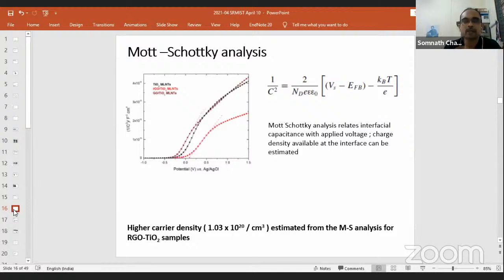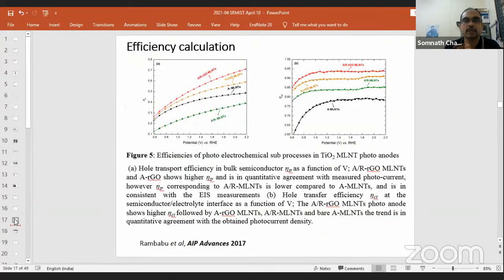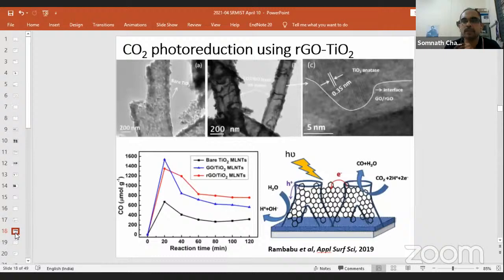Then we did a couple of other studies in which we did detailed charge density calculations, resistance calculations, and efficiency calculations, and we found that the graphene oxide wrapped TiO2 nanotubes actually help in enhancing the photoelectrochemical efficiency of the process.